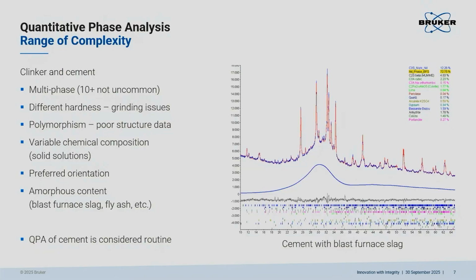Just two quick examples concerning the level of complexity you can deal with. This here is a cement. It has a large amount of amorphous phase, which is indicated here by this intensity distribution in blue. Clinker and cement, it is actually a solved problem. It is considered routine today. No way to do anything with single peak methods, obviously, because of the peak overlap. And there are additional issues. I mean, look at the background function. We will discuss that in more detail later. So 10 phases and more is not uncommon.